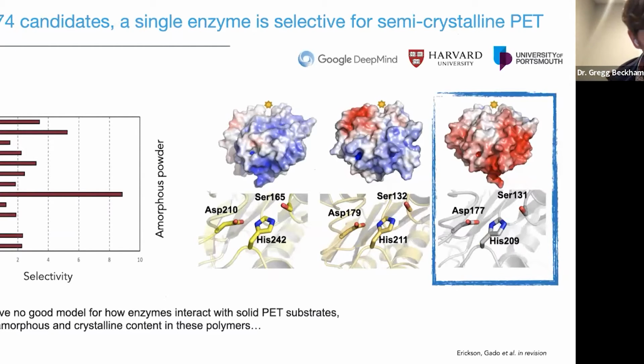And so we synthesized the genes and the plasmids for expression of all 74 of these enzymes. We went through purification trials with all 74, and we were able to get 51 enzymes that were able to be expressed, purified, and assayed for PET hydrolysis. And what we did was we assayed these as a function of temperature from 30 to 70 degrees C and pH from 5 to 8. And we looked for activity on two different substrates, an amorphous powder and an amorphous film, as well as a crystalline powder, so actually 3 substrates.